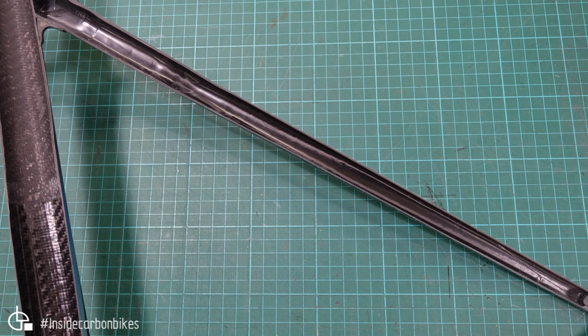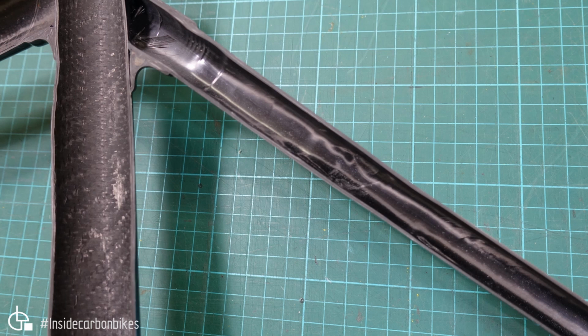And then the seat stay, you're moving up the seat stay. It's mostly good until you get to this area here where the brake bridge is co-molded, and then there's a bit of a lack of compaction and a void through there. So you can see some wrinkling through here, and a bit of a void. So that's indicating that the compaction wasn't quite uniform through there.